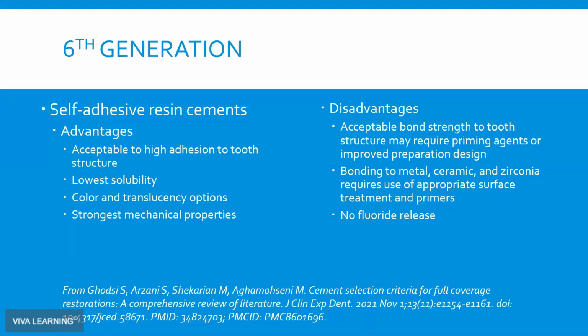So in the early era of the self-adhesive resin cements, I would have to say, unless you had excellent retention form, no short preps, no tapered preps. Just in case, we would put little boxes and lugs here and there to add more anti-rotational features and more surface area. Only because these self-adhesive resin cements, in hindsight, now that it's easy to armchair quarterback, the chemistry just wasn't there. It did do some bonding to teeth, no doubt, but for example, to prepped enamel, no problem. Etched enamel, even better. Prep dentin, and we saw the results of that, a lot of debonded crowns. And a lot of leakage, a lot of micro leakage. When those crowns came off, you can quite see the effect of that.